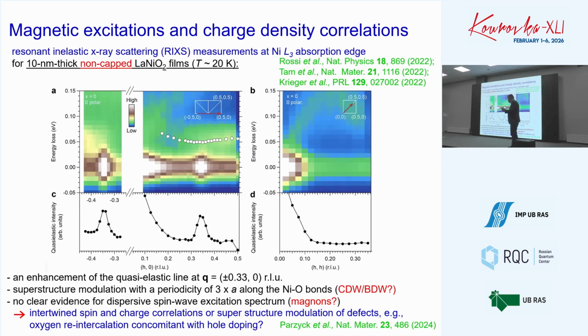The same experiment for non-capped nickelates shows completely different results. Although people claim that there is no clear evidence of dispersive spin wave excitation, I do see some kind of paramagnon-like behavior here. But what is most important, they saw some kind of evidence for, let's say, CDW formation with an unusual wave vector, Q 1/3, along, I think, the nickel-oxygen bond.